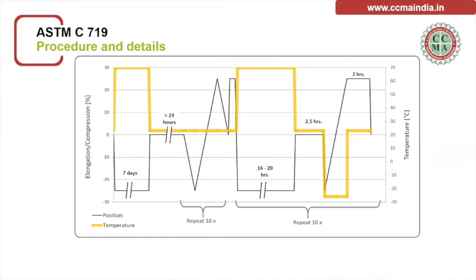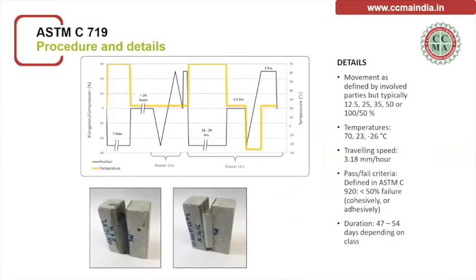This test is performed in various scenarios. It is extended from minus 25 to plus 25, and the temperature at which it is tested ranges from minus 26 degrees Celsius to 70 degrees Celsius. The traveling speed of the compression extension testing machine is 3.18 millimeter per hour, and the pass criterion is that there should be less than 50% failure, and the duration of the test may take approximately 2 months depending upon the class of sealant.